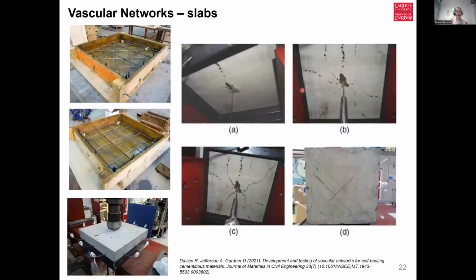We have then extended our work to vascular networks in slabs, so looking at orthogonal and diagonally placed reinforcement and vascular networks loaded with sodium silicate and tested these simply supported slabs under a centrally applied point load. And what we can see is that we had good flow of healing agent out of our vascular networks, and we managed to get some reasonable stiffness recovery of about 75%.